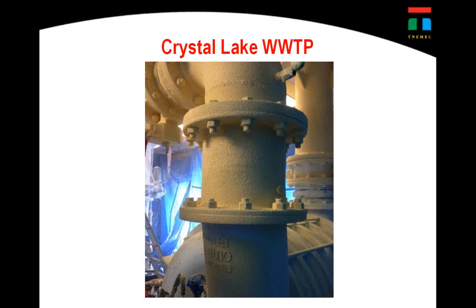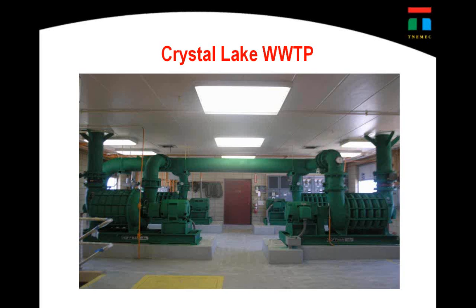Okay, so here's Crystal Lake water treatment plant, where they have a huge amount of equipment that's sweating all the time. And this is where we applied Aerolon to this entire pipe chase and piping gallery to eliminate that from occurring. This was a very extensive project, and we're seeing a lot of this done now even in normal mechanical spaces. So this essentially eliminates condensation and sweating from occurring. And is the finished product, already finished painted, as it were. And now they have no more insulation coating these pipes, no more falling off, none of it dripping.